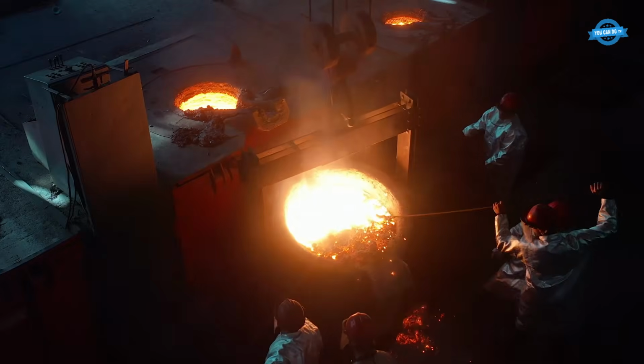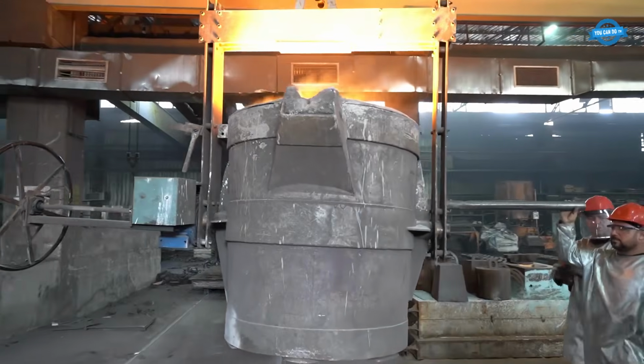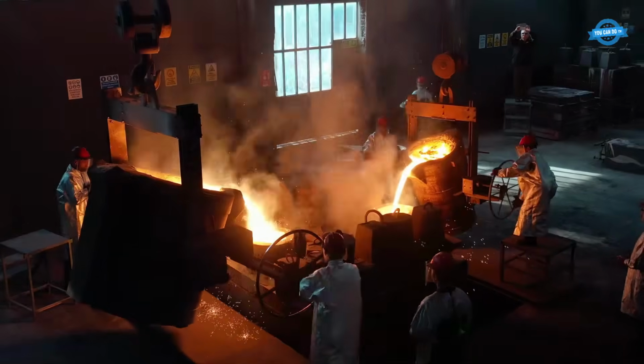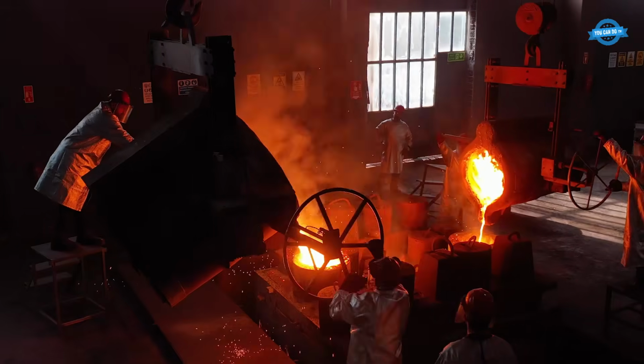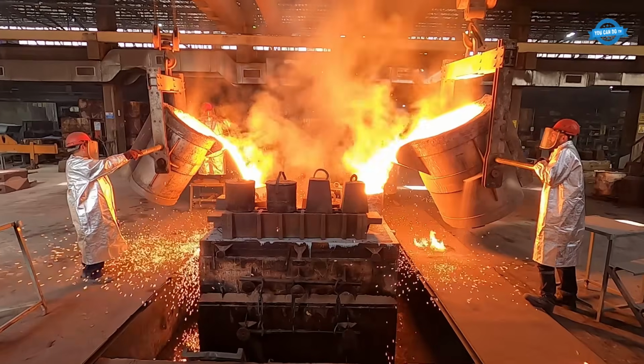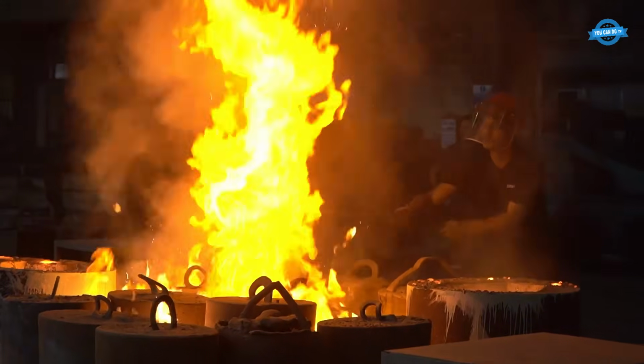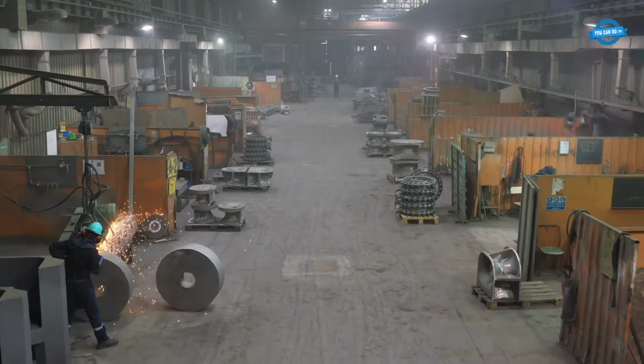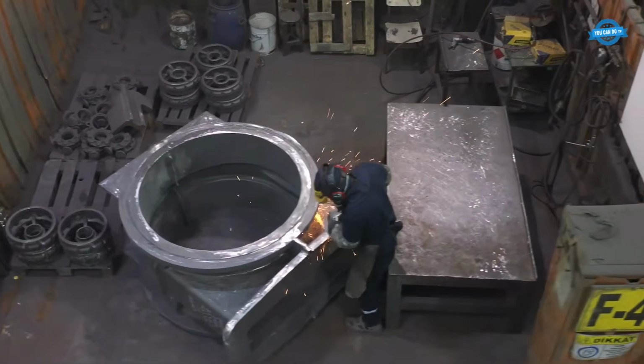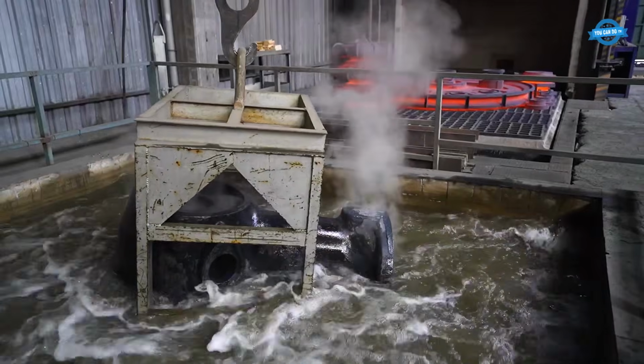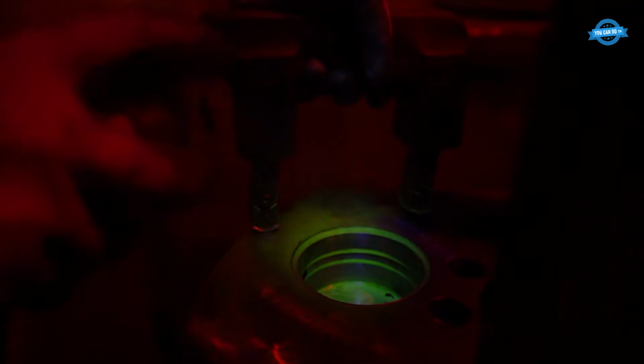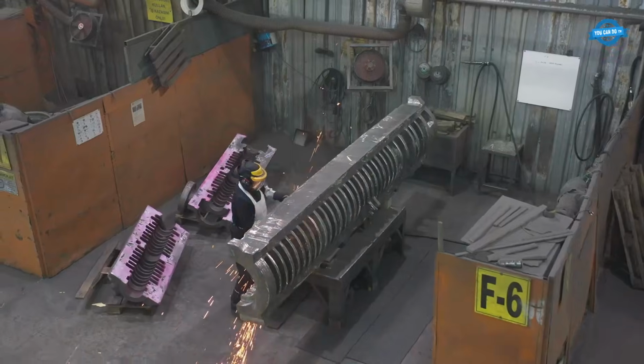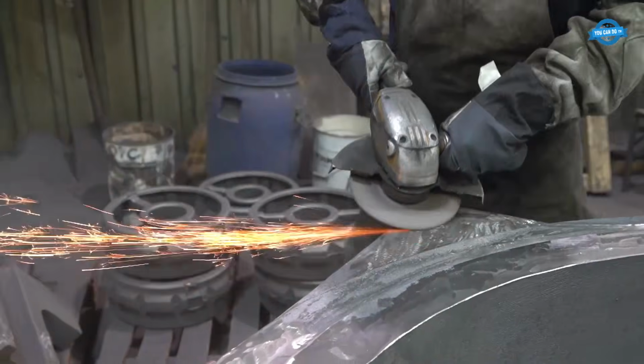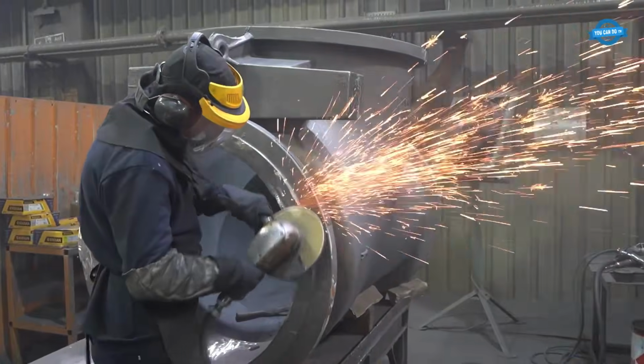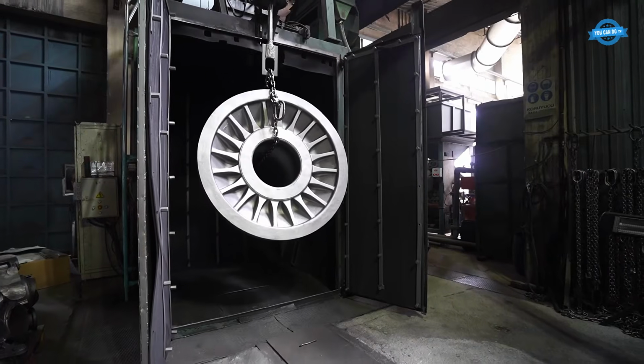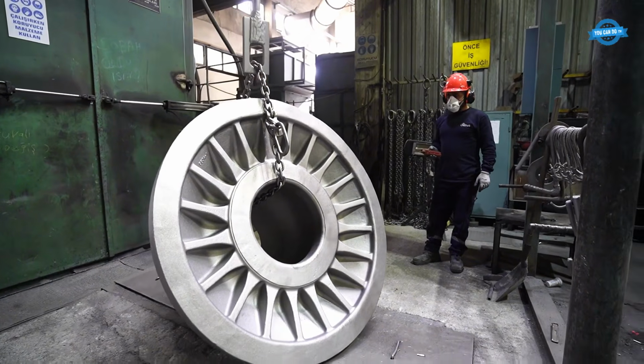CNC machined wood or composite patterns define the geometry every casting inherits. Induction furnaces hold metal near 1,565 degrees Celsius, while spectrometers verify chemistry before pouring. After solidification come heat treatment, quenching, tensile testing, ultrasonic inspection, and liquid penetrant testing to find cracks or internal defects. Finished castings move to CNC machining, final QC, certification, and international shipment for load-bearing equipment.